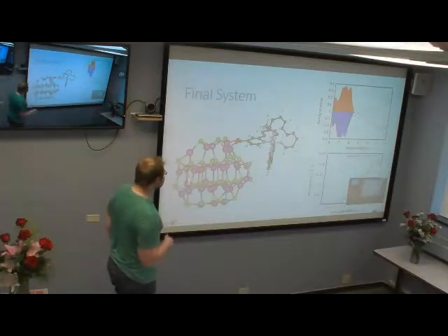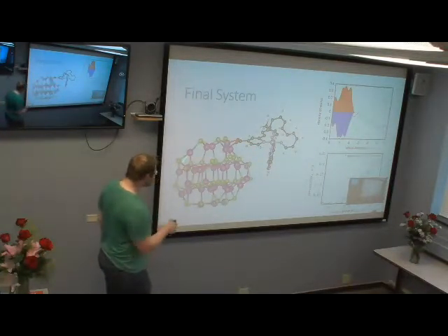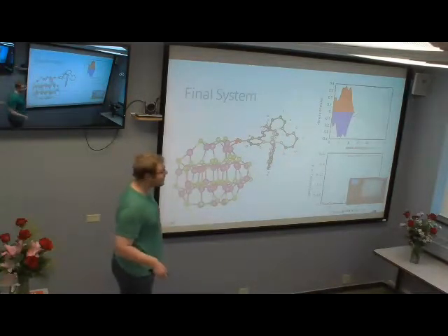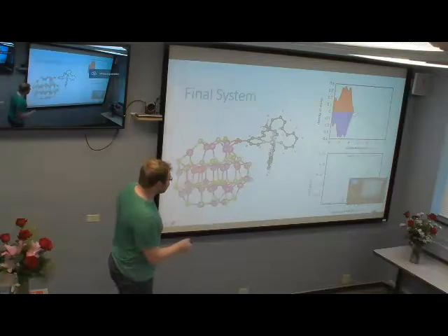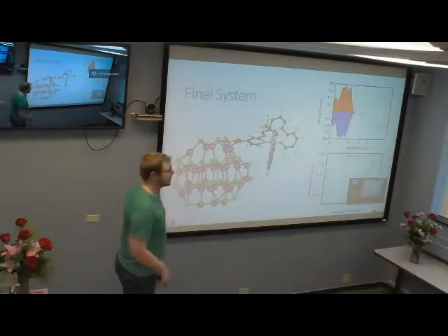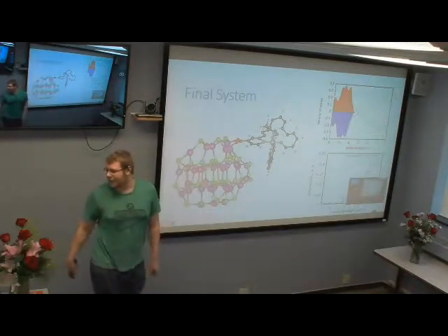So after we heated it, we get some breakup of the dye. The bipyridines broke quite a bit, but the quantum dot didn't change all that much. Density of states changed quite a bit. Most notably, the band gap is gone. We don't have a band gap. And there's some stray low energy states in the absorption spectra, which I'll talk about what that might mean a bit later. So here we have the dynamics. It's pretty short, but it's all moving around.